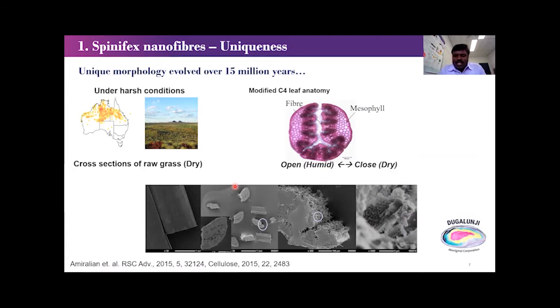Okay, so what is unique about the Australian spinifex nanofiber? Spinifex grows, as you can see on the Australian map, in the northern part of Australia. It has survived for 15 million years, and in extreme conditions it has evolved a very unique leaf anatomy. It has to survive really hot conditions, up to 55 degrees or so. In dry conditions, the spinifex grass leaf closes tightly, and that holds the water inside the leaf, and it survives.